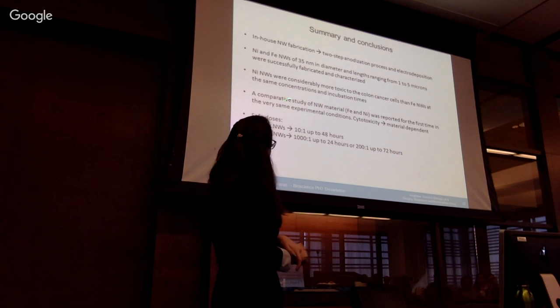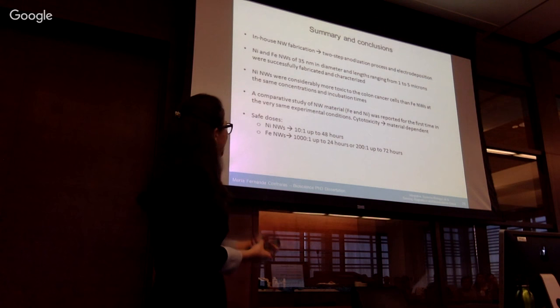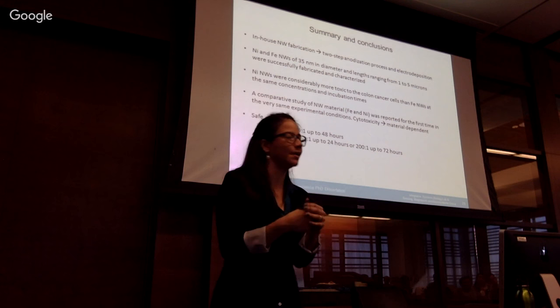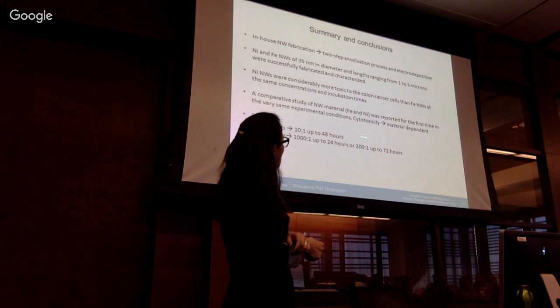And a comparative study of nanowire material, the two materials I mentioned, was reported for the first time under the very same experimental conditions. So people always say that iron is better than nickel, but they never actually proved it under the very same experimental conditions. So from here, we can conclude that the toxicity associated to the wires has a lot to do with the material.